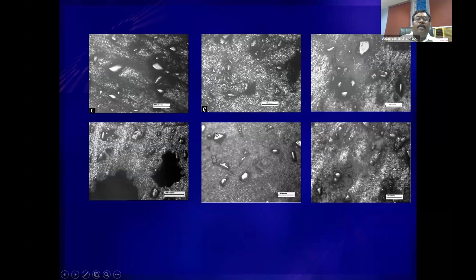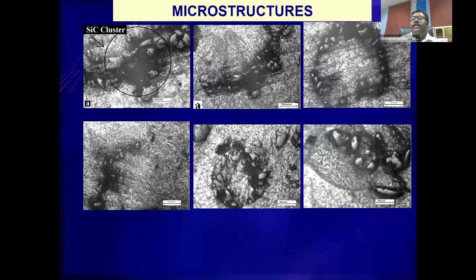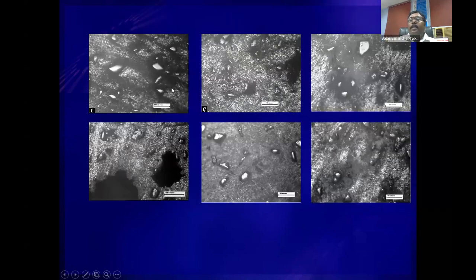And when you have so many agglomerations, one thing that is noticed here is a lot of porosity associated with the agglomerated structure. Because the melt will not be allowed to go inside the agglomerated structure, the melt will be stopped here. It's a barrier. As a result, you form some porosities associated with the particle clusters. But when you have uniformity, a homogeneous distribution, you can also minimize the porosity, and you can expect good mechanical properties with this processing condition.